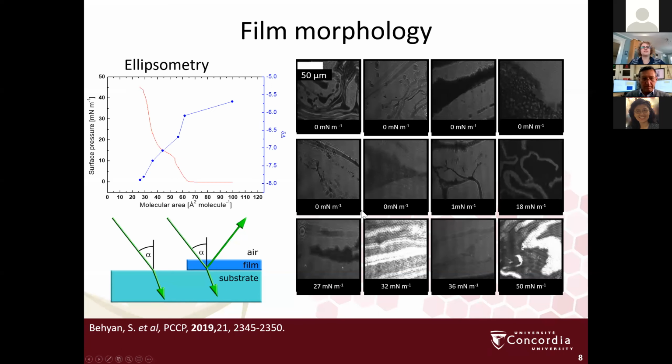So nothing really changes, except that after the plateau, periodically, and increasing as we go up in pressure, we start to see these very bright regions associated with the fracture lines where domains have come together. So we get these striated collapse material occurring on those phase boundaries.